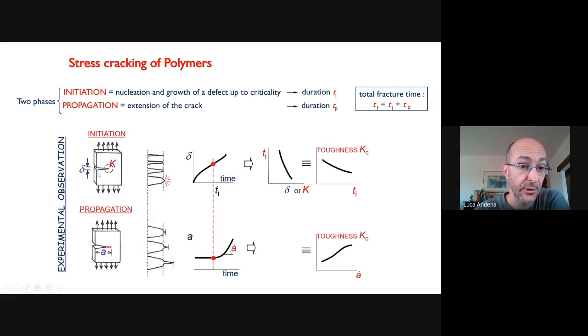This is what you observe. You have a stress intensity factor, and at some point after blunting, it will become critical. Of course, the time for initiation will be lower if you apply higher load. But the characteristic property of the material is this relation between the toughness and the initiation time. Not a single Kc value, but rather a curve.